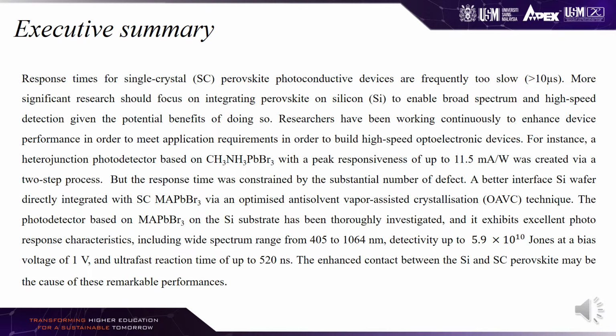The photodetector based on MAPbBr3 on the silicon substrate has been thoroughly investigated, and it exhibits excellent photoresponse characteristics, including a wide spectrum range from 405 to 1064 nanometers, detectivity up to 5.9 times 10 to the power of 10 Jones at a bias voltage of 1 volt, and an ultra-fast response time of up to 520 nanoseconds. The enhanced contact between the silicon and single crystal perovskite may be the cause of this remarkable performance.